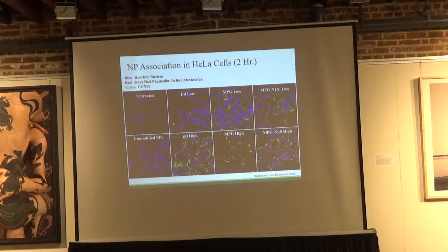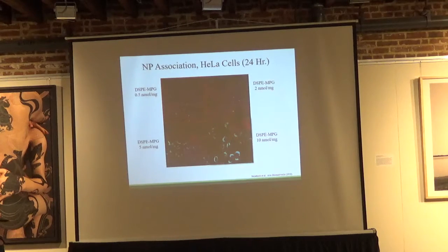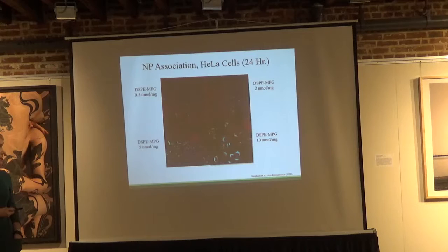We took one of these, we ran flow cytometry data I'm not showing here, and we identified that the MPG-coated particles provided the most increase in cell internalization. So we also verified this with different modifications on the nanoparticle surface, and saw as we increase the amount of MPG on the nanoparticle surface, we can obtain much greater amounts of nanoparticles, here shown in turquoise, within the cells. In fact, we could increase cell internalization by about 70-fold.